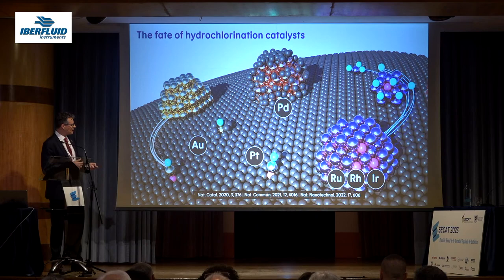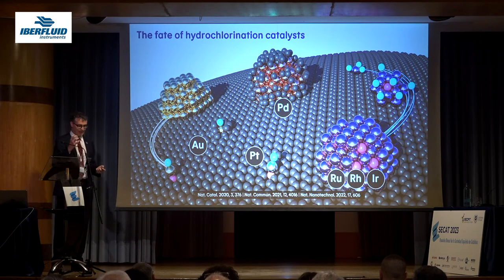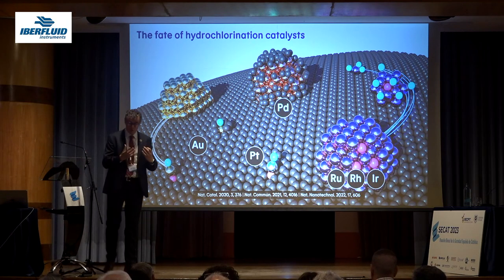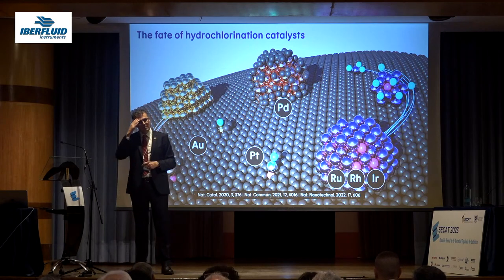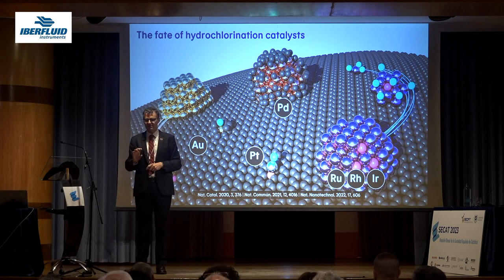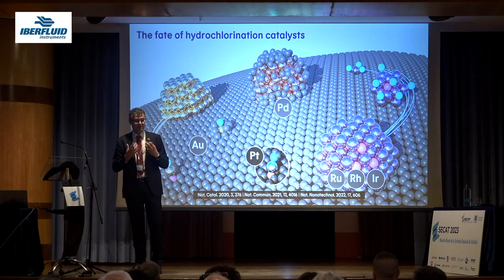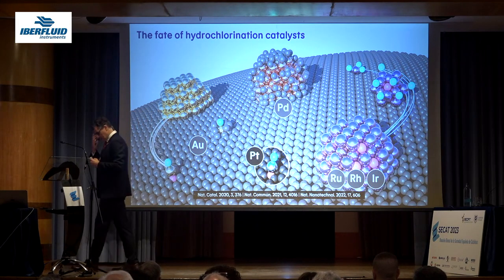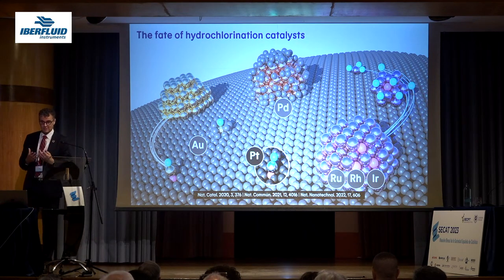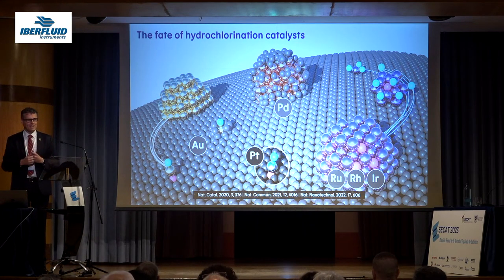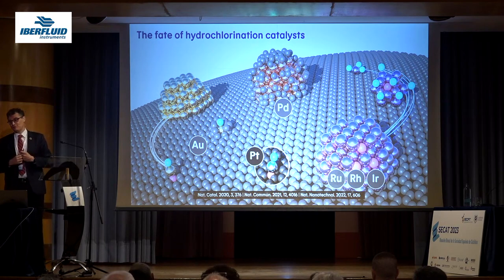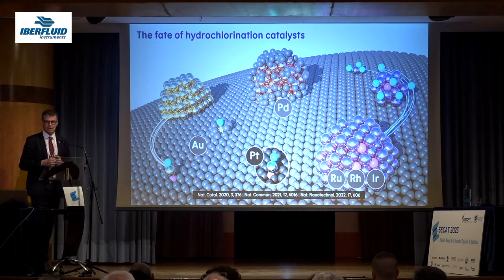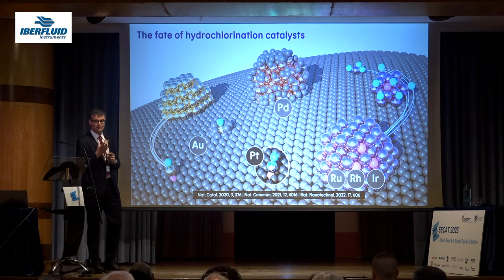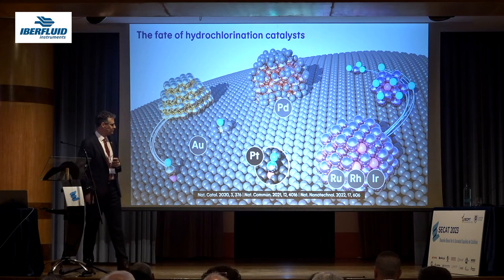And if you just stabilize gold on nitrogen heteroatoms on the carbon, you will coat them. So it's very, very difficult. So you remember in the graph that platinum was ostracized. Platinum was never touched because it was always the loser in this correlation. But platinum is the only material that is stable under reaction conditions. So a metal that has not been studied because it was put in the wrong nanostructure, probably as a nanoparticle. If it's in single atom form, it's quite active, and most important, very, very, very stable.